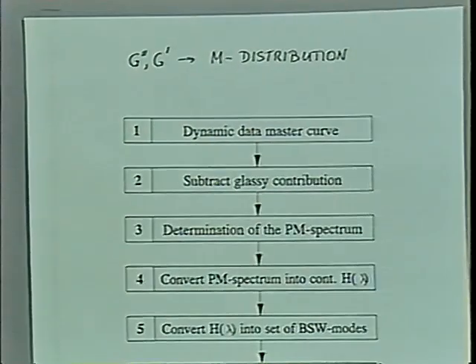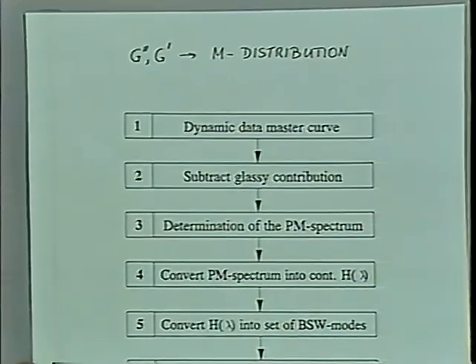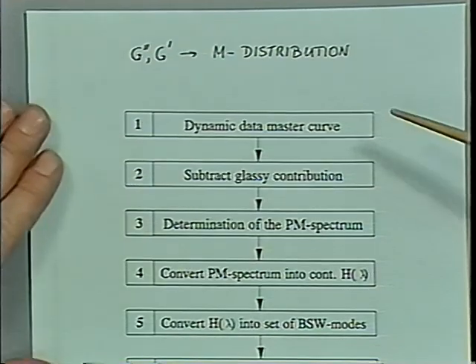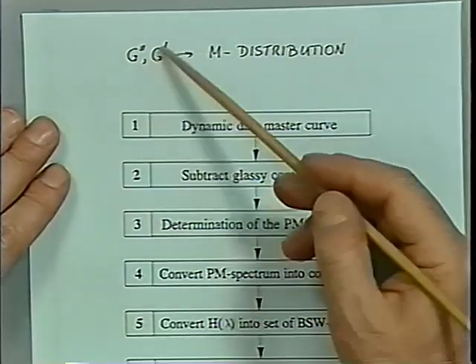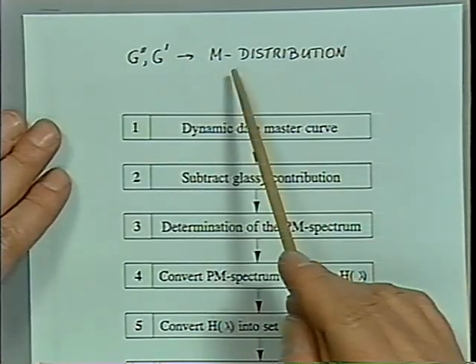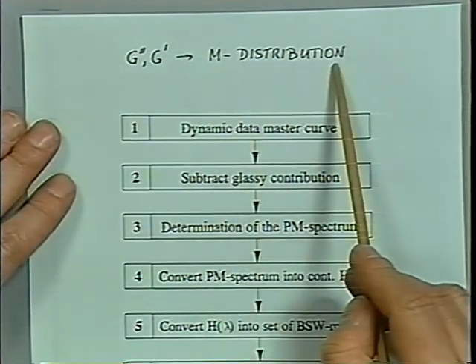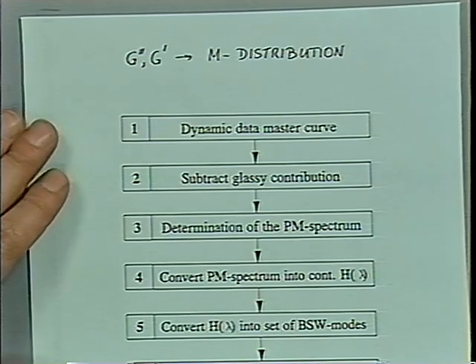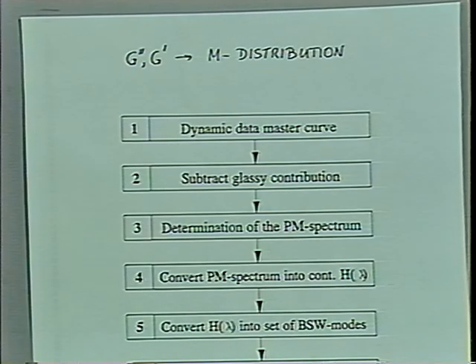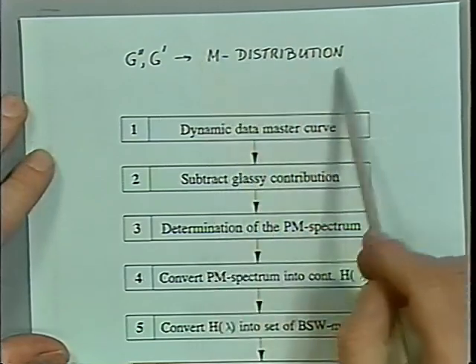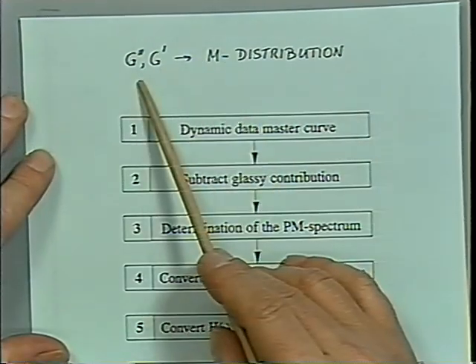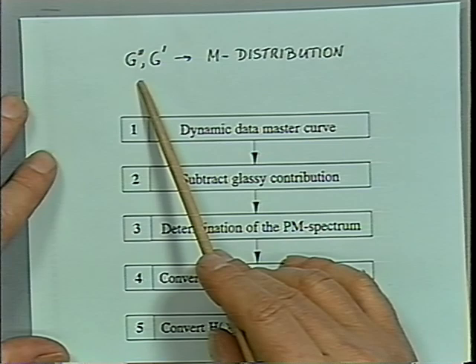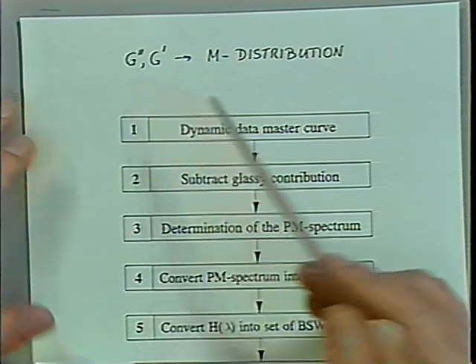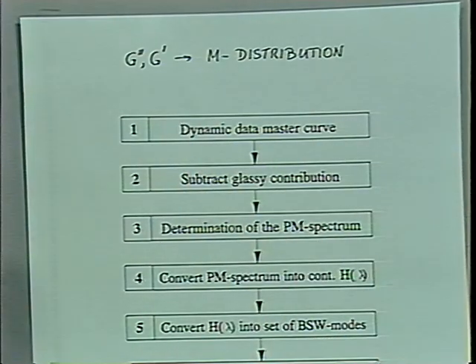To describe now our overall approach, the dynamic data, G prime, G double prime, should be converted into a molecular weight distribution. That's really what we would like to do. Before that, Michael changed the molecular weight distribution and looked at the effect on G prime, G double prime. But now we want to reverse that and make rheology useful as a tool for determining molecular weight distributions, say, of polymers which cannot be put in solution.